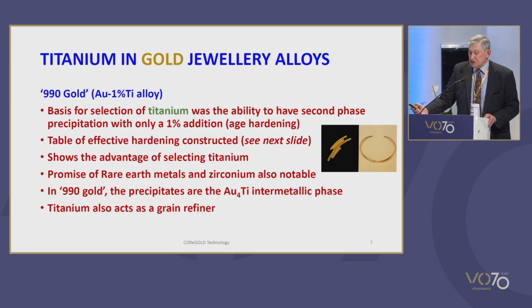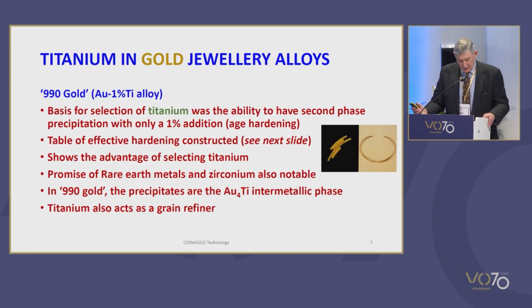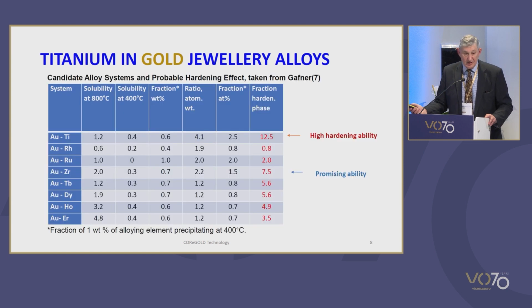The basis for selection of titanium for this alloy was the possibility of second phase precipitation, as an alloy containing 1% alloying addition in solution was cooled from 800 to 400 degrees Celsius, i.e. its age hardenability. From this, a table of probable hardening effectiveness was constructed, which we can see in the next table.